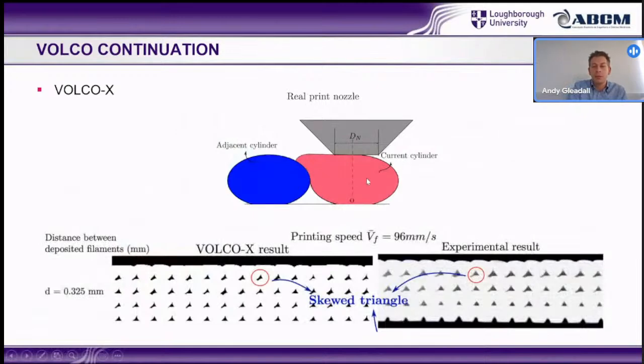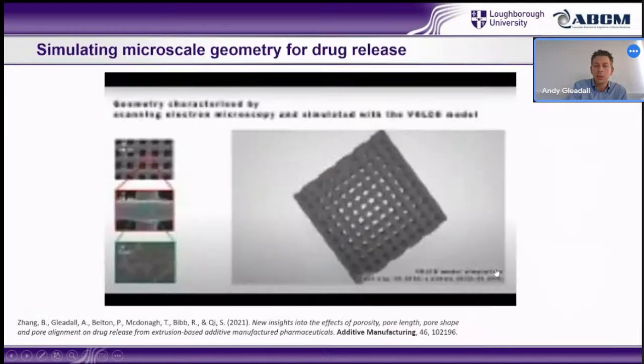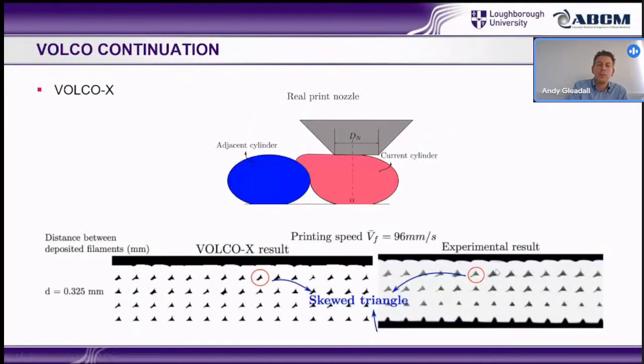This was an algorithm optimized for filaments being deposited side by side, where this strange thing happens. In this structure on the bottom right, this is the experimental image, you can see the filaments have quite an odd shape, and it's because it's printed from left to right. When it prints the next filament along, it's easy for the polymer to go on top of the filament, but not so easy for it to be squashed underneath. So you end up with these triangle-shaped pores, and that's what his deposition strategy factored in.